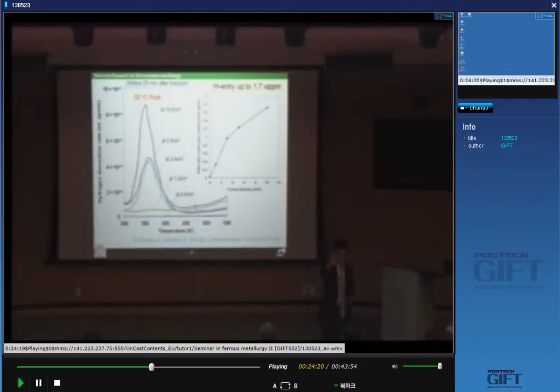Usually a researcher emphasizes that hydrogen can move or diffuse so quickly. But that is the case in ferritic steel. In austenitic steel, hydrogen diffusivity is very low, at least four order magnitude lower than that of ferritic steel.